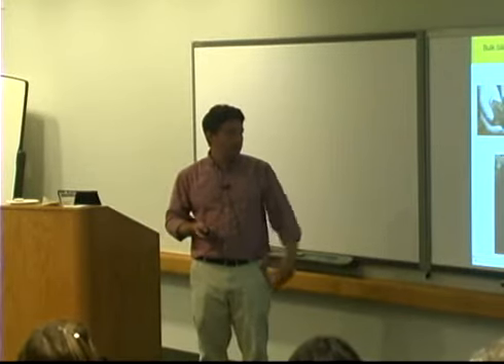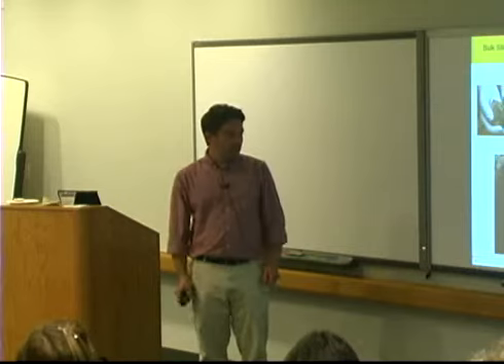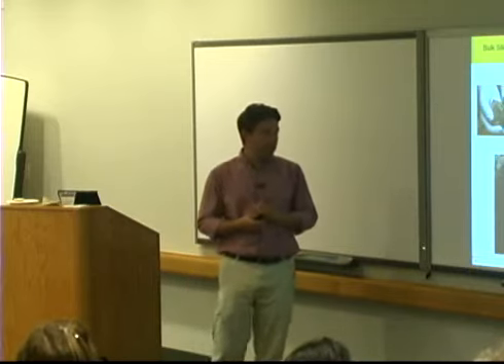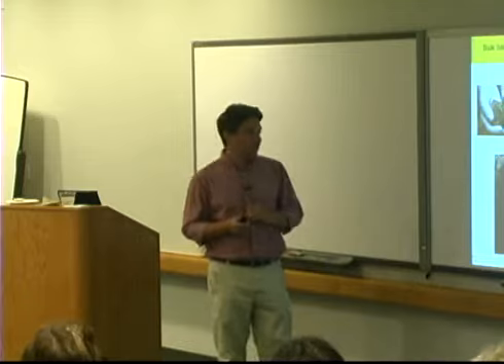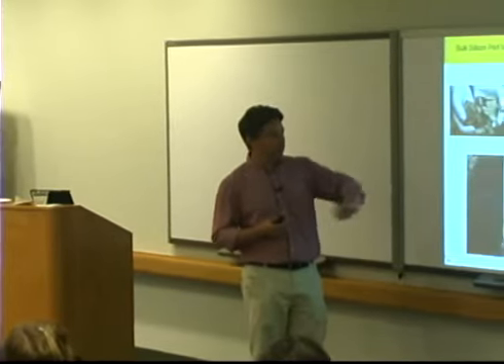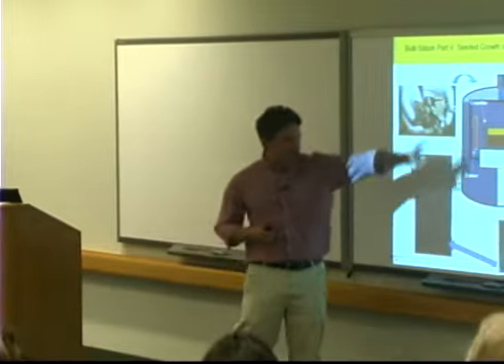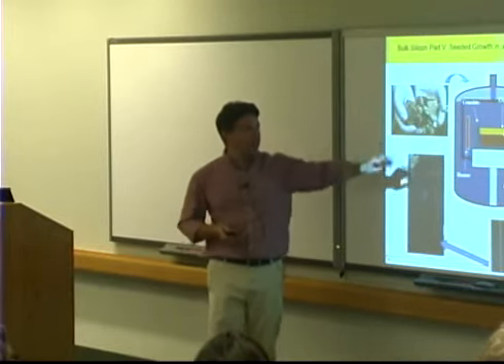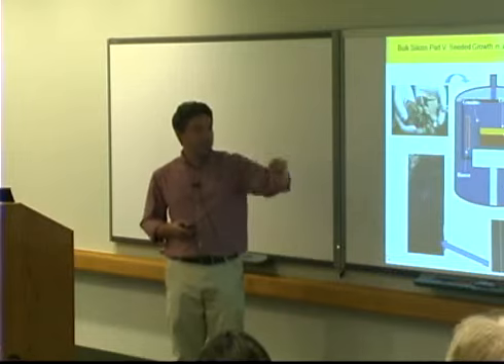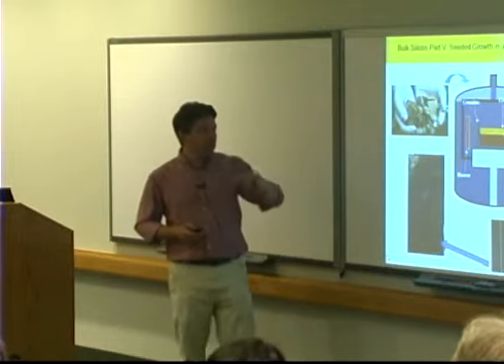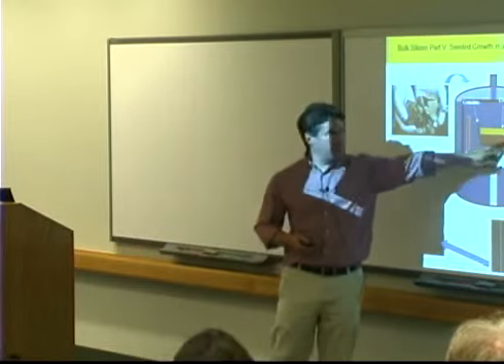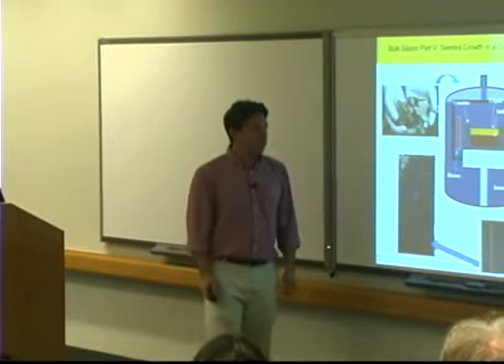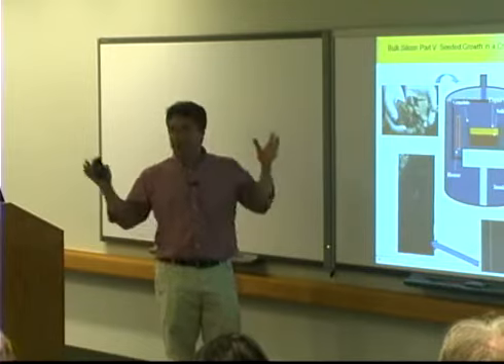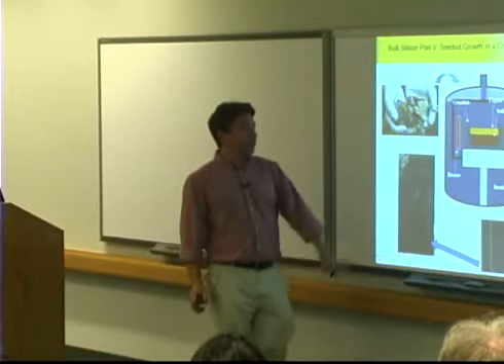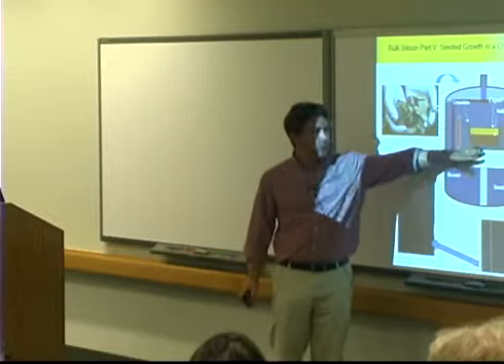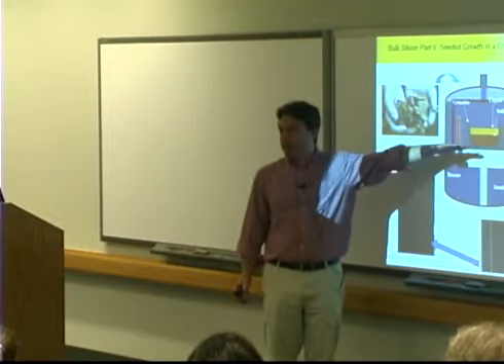So now we come to what I worked on at BP Solar. This is a technique that I developed, and basically it starts with all the same things as the multicrystalline case. Same feedstock, same furnace, same crucible. And the difference is that you place a seed crystal at the bottom here. And instead of just melting everything down, you have to keep the seed crystal somewhat cooled while you melt everything else on top of it.